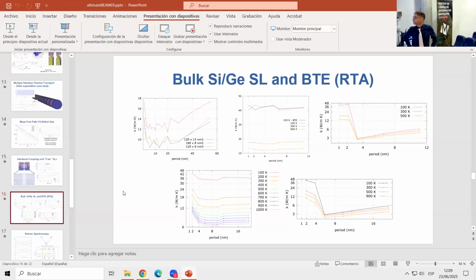And then the BTE is also tricky to use. I also wonder if it's exact. The BTE is exact. It can be derived exactly from quantum field theory, but then you need to perform approximations in order to use it and to simulate and to plug in the interface, the thermal boundary resistance. That's right. So we know that the BTE works in the bulk. We can compute it with DFT, and it predicts the bulk conductivity. But when it comes to boundary conditions, exactly.